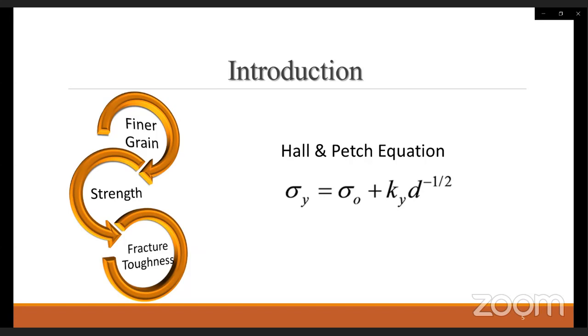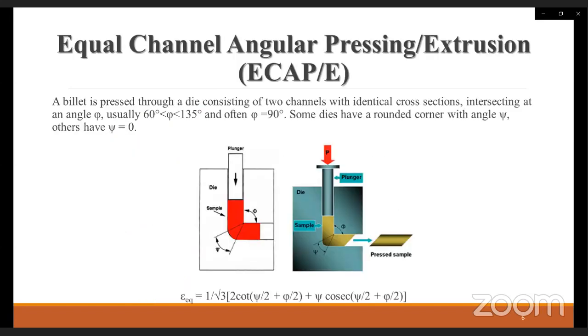the ECAP. So let me just explain the ECAP die briefly. We have a billet that is pressed through a die consisting of two channels with identical cross sections intersecting at an angle of between 60 to 135 degrees, and we have a rounded or zero corner.